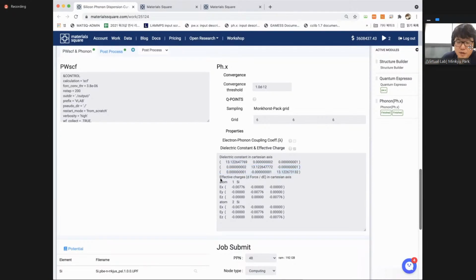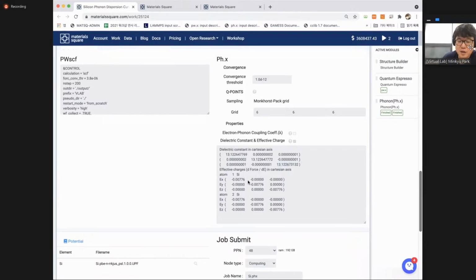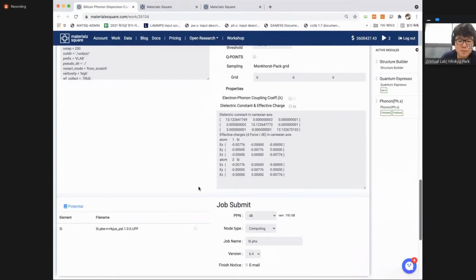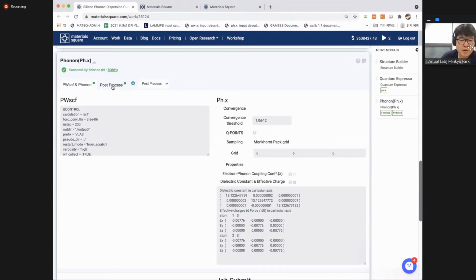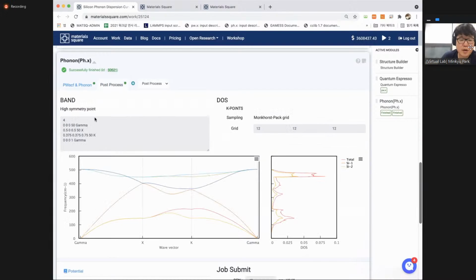And also you can check the effective charge in the Cartesian axis for each atom. And these diagonal components are the same. So it means this material is not anisotropic, but isotropic. Okay. So, and you can press post-processing. We calculate the band structure and density of states.